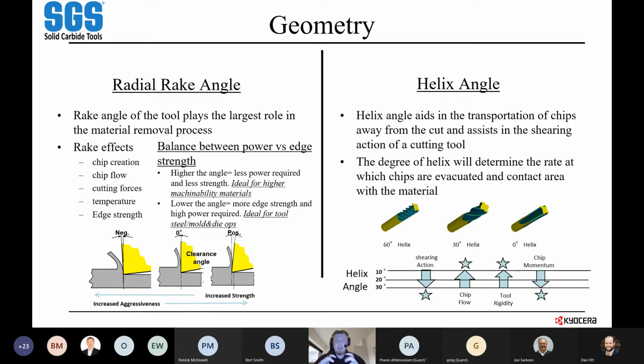But as you increase that twist, now you're going to have more flutes in contact with the material at one time. So now you have extra contact, potentially need a little bit higher horsepower requirement or a little bit more rigid setup. So those are things that you kind of have to balance out there. That degree of helix will also add some rigidity into the tool as you get lower into low helix or even straight zero helix. You're going to have a much more rigid tool than something with a really fast twist. So this is all about balancing out tool stability, workpiece contact, and then also that shearing action. That's the goal, but you can't lose out too much on either side.